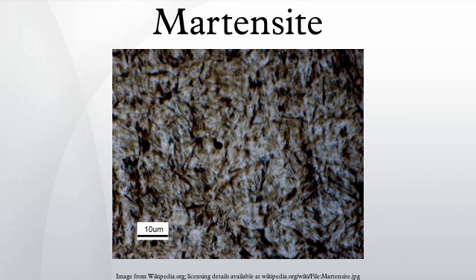In certain alloy steels, martensite can also be formed by the working and hence deformation of the steel at temperature in its austenitic form, by quenching to below Ms and then working by plastic deformations to reductions of area to 40 percent or as little as 20 percent of the original. The process produces dislocation densities up to 10^13 per centimeter squared. The great number of dislocations, combined with precipitates that originate and pin the dislocations in place, produces a very hard steel.